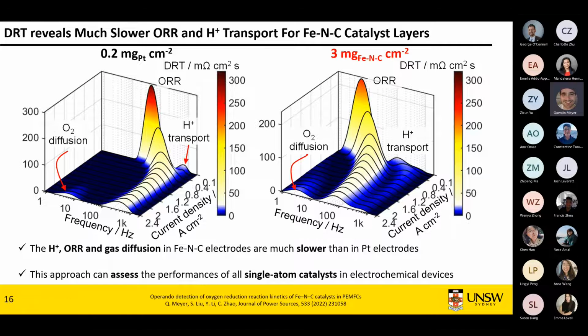So instead, what I've done is I used my very fancy new DRT technique, and then I did a little bit of MATLAB to basically measure the points, the black lines, and interpolate what's happening between the lines to get an idea of a continuous process. And so the first thing we see on our platinum catalyst is you get proton transport limitations at very low current densities that eventually can't be detected anymore. You've got an ORR peak at about, I think, somewhere around 50 Hertz that slowly merges with proton transport limitations at high current densities and some gas diffusion problems.